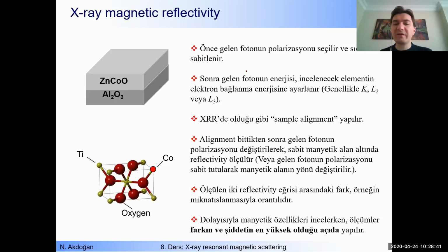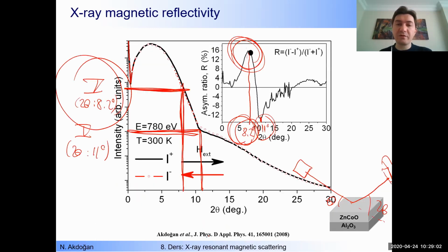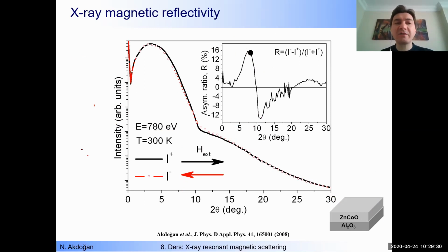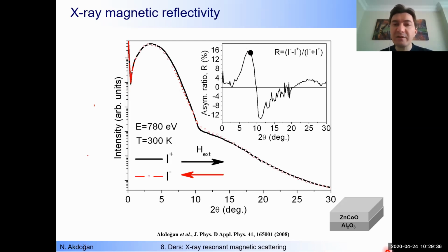So it is also explained here. We select the position where the difference between the curves and the intensity are maximum. So as you see here. Any question here? Did you understand that point? Okay, we have carried out X-ray magnetic reflectivity measurements, and then we have found that this position is the best for me to continue, because at that 2 theta and theta angles, I can get the maximum difference between two curves, okay? And then I can get the maximum signal at that angle, maximum intensity, let's say.